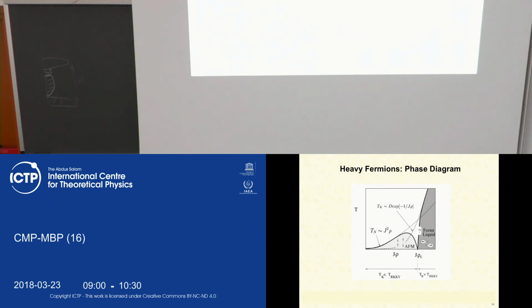What I said actually is summarized in this phase diagram. You can plot the effective temperatures. The magnetic phase effective temperature, or Néel temperature, is given by RKKY. It is just second order perturbation of the Fourier transform of the Lindhard function. For the Kondo effect, it's a bit more complicated. This perturbation theory can be resummed or solved by means of the renormalization group equation, which leads to a certain scale which resembles very much BCS. So you see that this is non-analytic in the coupling constant J, but this is an exponential function.